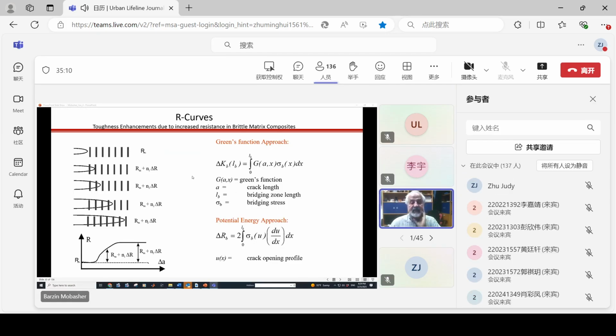So the way we have been looking at these mechanisms has been done by looking at R curves. R stands for resistance. And the R curves basically allow us to look at how toughness enhancements form due to increase in resistance. So imagine you have a crack that's propagating and there are a bunch of fibers sitting here along the length. As the crack hits a fiber, the first fiber adds some extra energy. So the initial resistance is increased by 1 fiber. If it hits the second fiber, now it's 2 fibers. Then it's 3 fibers. But by the time it goes through, now the first fiber also gets pulled out. So the first 2 fibers now are not carrying any load.